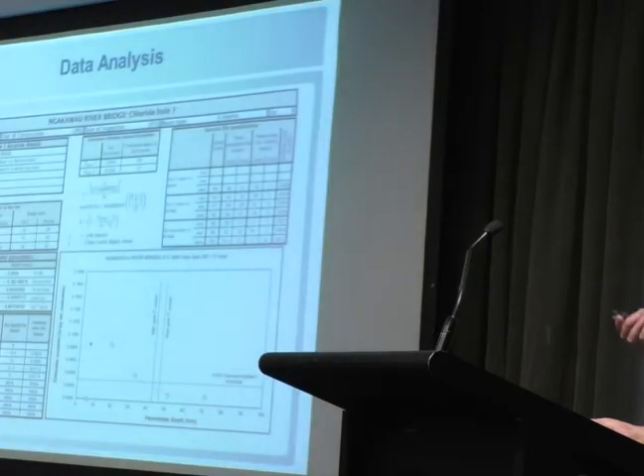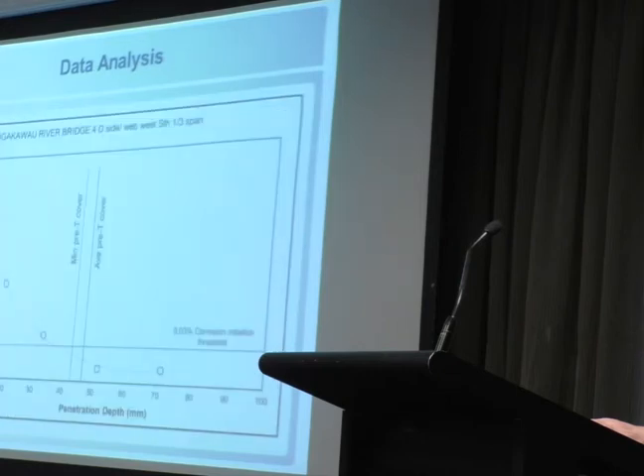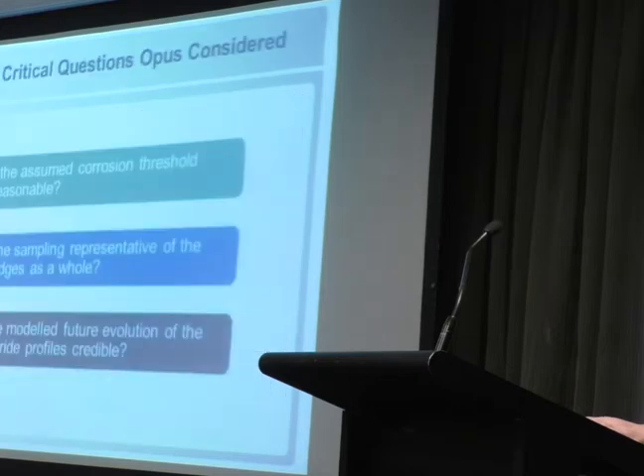So this is the kind of thing Rhys did. It was very, very straightforward. As I said, he plotted chloride concentrations against depth. He assumed a particular chloride concentration threshold. He measured the cover to the critical reinforcement, so the pre-stressing, and calculated the length of time that remained until the chloride concentration at the pre-stressing exceeded those thresholds. So fairly routine. So when Opus looked at this work, we had three main questions.